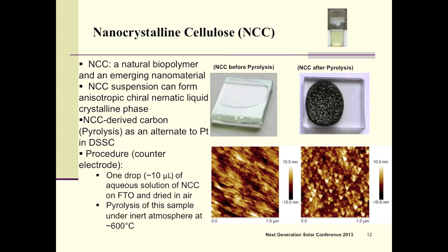properties. For example, the suspension of NCC can form an anisotropic chiral nematic liquid crystalline phase, and we used carbon derived from the pyrolysis of the NCC in our counter electrodes to replace platinum, and these are our initial results. You can see the pictures of the NCC before pyrolysis, and below are the AFM images that show the morphology. Before pyrolysis it is a rod-like needle structure, and after pyrolysis it is a kind of round morphology.